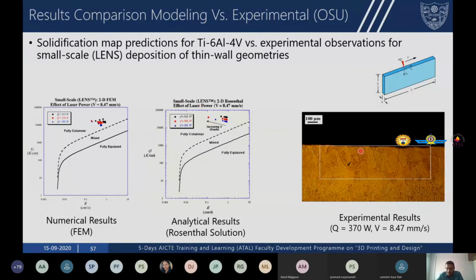And this is the experimental result obtained at 370 watt power, which falls within the set of process parameters considered here. And you can see that experimental results are showing a fully columnar morphology. And if you look at the modeling results, it's also showing a fully columnar morphology, that is long and elongated grains as shown in experiments. So the modeling results are in good agreement with experimental observations.